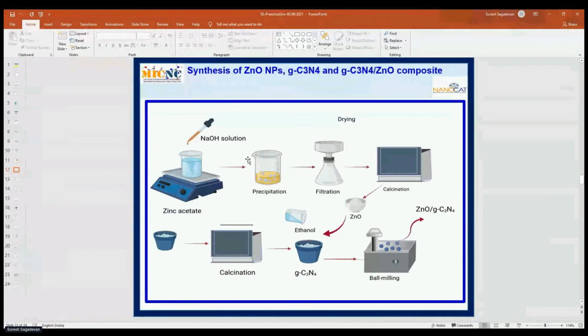A thermal polycondensation process was followed to prepare this graphene carbon nitride. About 5 grams of melamine in the form of white powder was heated at 550 degrees Celsius for 3 hours in a muffle furnace. After this period, the formation of yellow powder confirms the formation of graphene carbon nitride.